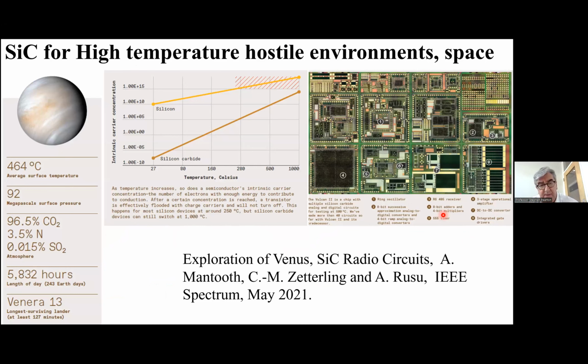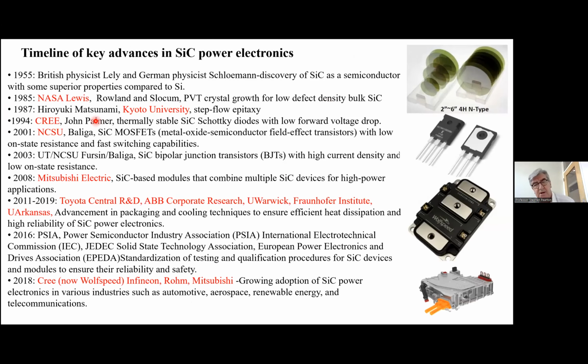I also refer you to the fact that silicon carbide can operate at very high temperatures. So it doesn't go intrinsic even up to 1,000 degrees. There's an article in IEEE Spectrum from a couple of years ago from Alan Mantooth and Carl-Mikael Zetterling on the development of a silicon carbide-based chipset that is going to be used in NASA missions exploring the surface of Venus, which is a very high temperature, high pressure, kind of aggressive environment. But silicon carbide can do that, whereas silicon could not, because above 200 degrees, silicon becomes intrinsic, and you can't switch the devices.